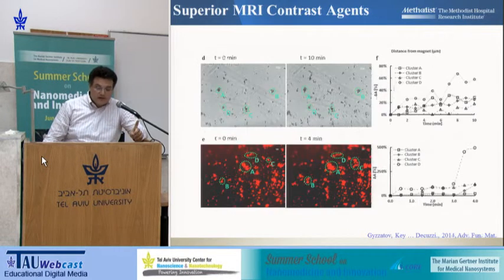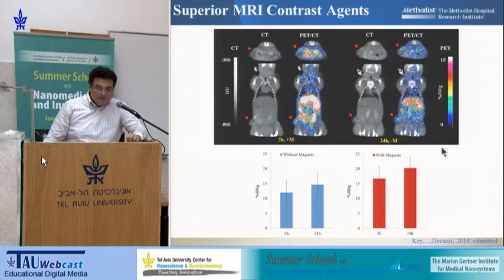And now you can use magnetic drugging in vivo, and these are very recent data from last week showing with the Discoidal Polymeric Nanoconstruct that you can get all the way up to 20% of the injected dose and even larger, 25%, in only 24 hours. Previously, it was 48 hours. We were getting 20% at 48 hours. Now we are accelerating the process of deposition into the tumor. 24 hours, already 15% in 3 hours. And 3 hours is the time that we're keeping the magnet on the tumor of the animal. So if we can keep it probably longer, then this can become 30%, 40%. And now we are using just magnetic drugging, no ligand receptor interaction.